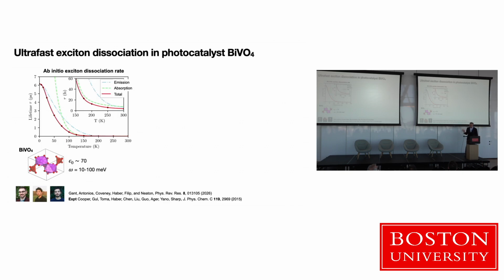The other thing one can do, and this is another example of an observable, is calculate the exciton dissociation rate. So this is when you create an exciton with a photon, then that exciton can scatter with different phonons and gain some finite center of mass momentum. It can also decay via other channels. What we would like it to do is decay into a free electron and hole pair. And we can do that. We can compute the probability of that and the lifetimes associated with that as a function of temperature with this formalism. And so you can see that there's a picoseconds to femtoseconds change in the lifetime as a function of temperature, suggesting a very ready dissociation.